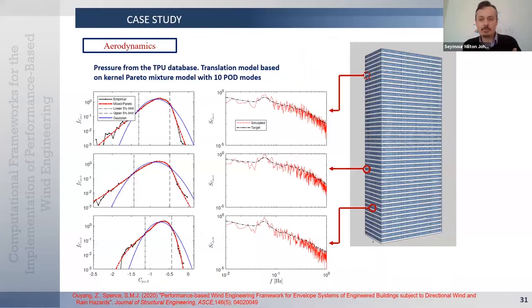So what we have here is just some representative illustrations for some pressure coefficients over the building height. So here, if we look at the three plots that are on the left, what we're looking at are the marginal PDFs, probability density functions of the pressure coefficients. So in blue, we have the Gaussian PDFs of the local pressures. And then in black, we have the actual target data. So you can see these are highly non-Gaussian. So local pressures are generally highly non-Gaussian, so it must be captured if you're looking to calibrate the stochastic model. In red, we have our proposed models that we are using based on that kernel-Pareto mixture. You can see that we very easily capture the non-Gaussianity in the pressures.